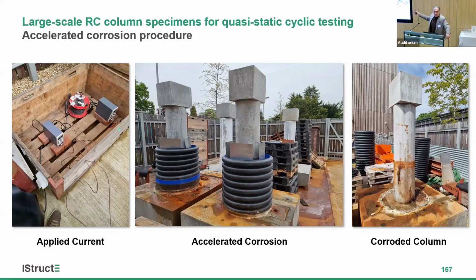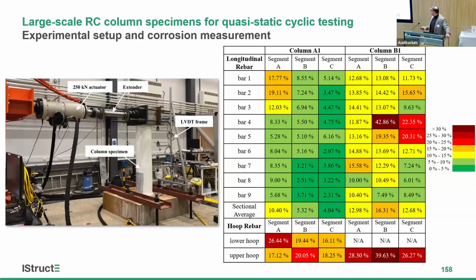How we accelerate it and at what rate, we have to be realistic, because if we accelerate it too much, it will explode the cover too quickly, which is not realistic. If we do it very slowly, it takes too long. Based on the experience that we had, the measure is called corrosion current density, roughly around 200 microamps per square centimeter of reinforcement surface area. There are some papers that have done parametric studies, and over the past 15 years I've been doing this, that's about right. After the corrosion, you will get something like this. You see the vertical bars and the corrosion products coming out. This is the test setup.